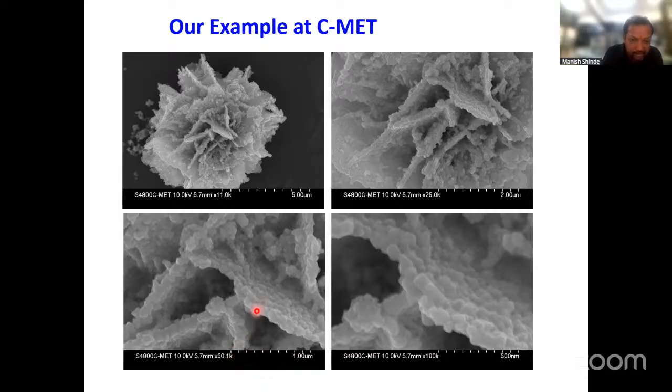Now if you look at this petal thickness, it is around 100 to 200 nanometer thick. Okay. Again, we may feel that it is not nanoscale feature, but this petal is not made up of a sheet. It is made up of tiny particles, small particles agglomerated. So again, I magnified further. I went to 1 lakh magnification. Scale is 500 nanometers. So distance between these two lines is 250 nanometer. Now, if you look at these particles, the particles are 50 to 100 nanometer in length or size, diameter.